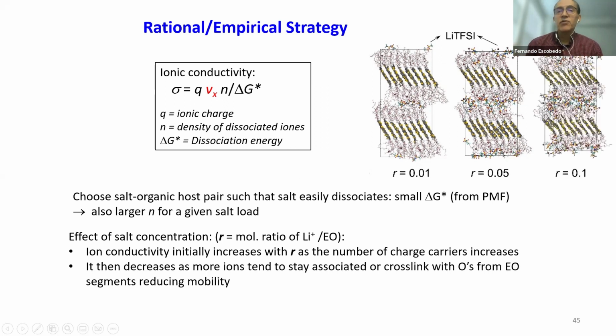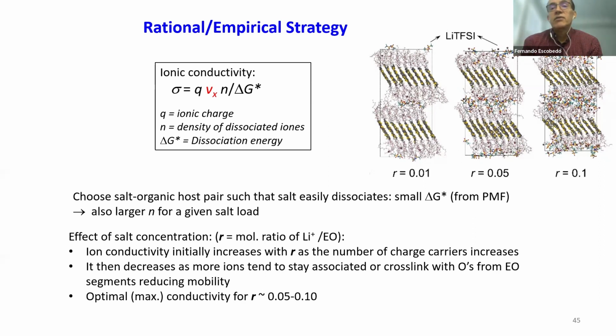But only up to a point. By the time you keep increasing this R, the conductivity starts decreasing. The reason is that some of those additional ions just stay associated, so they don't contribute to ion conductivity. Many of them start cross-linking with the oxygens in the ethylene oxide units. So they are gelling the material and reducing the segmental mobility that would be important for these ions to move through this layer. So there is an optimum, which usually happens around R of 0.05 to 0.1. This has been found experimentally, and simulations also support some of these observations.